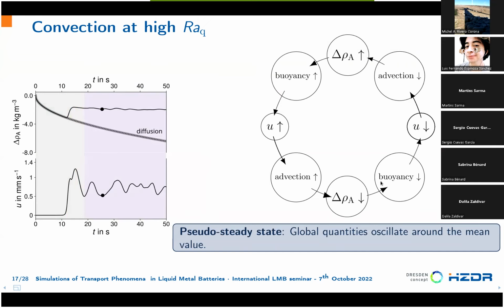This oscillation can be explained with this simple phenomenon. So the concentration difference, for example, decreases. This decreases the buoyancy term in Navier-Stokes, so the buoyancy forcing reduces, this reduces the velocity, which reduces the advection. Less advection means that larger concentration differences are established, and then this means more buoyancy, acceleration of the flow, more advection, and resulting in less concentration difference in the layer. And of course, diffusion plays a role here, and it smooths things out. So we don't have perfect oscillation here. The oscillations follow a relatively complex time evolution.